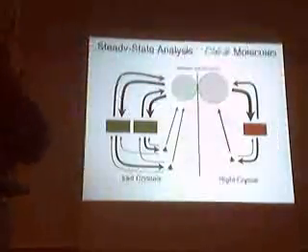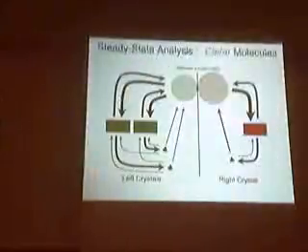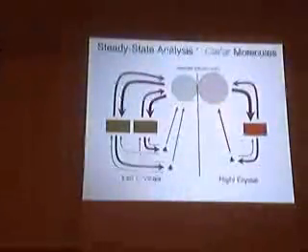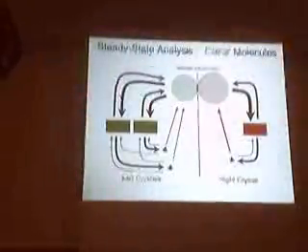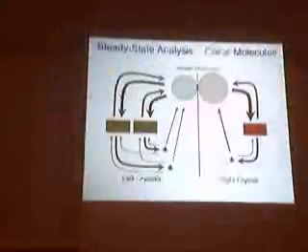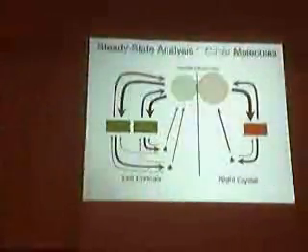But this does not require a steady growth in size. If after grinding for 3 weeks, the size of the crystal stops changing, this mechanism still works. But, I mean, in a sense, Ostwald ripening is the same because it talks about subcritical and supercritical. To the extent that that's what you mean when you say Ostwald ripening, I agree. But if you require the crystals to keep getting bigger, as they do in traditional Ostwald ripening, then I think that's not required in this case. That's why we call it attrition enhanced, because you need the attrition to see this effect. Yeah, you have attrition enhanced dissolution, which is retarded by absorption. And the more absorption, the slower the net dissolution.